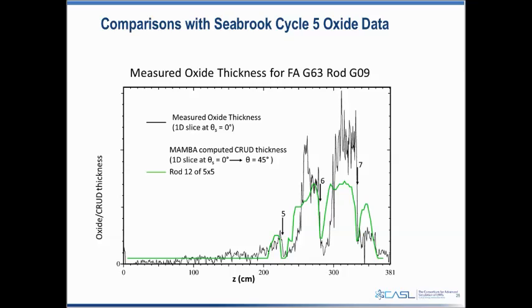You see we're in pretty good agreement as far as the axial distribution of crud. Now, the black would be a combination of the clad corrosion or clad oxide thickness and crud on top of that. In Mamba, we're not predicting that clad oxide corrosion layer thickness, so that's why the peak values measured are greater than the predictions there. But you see, axially, we predict it in the right locations and about the right magnitude as well.